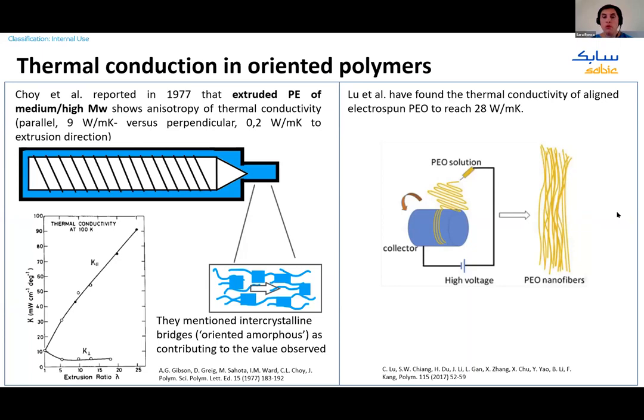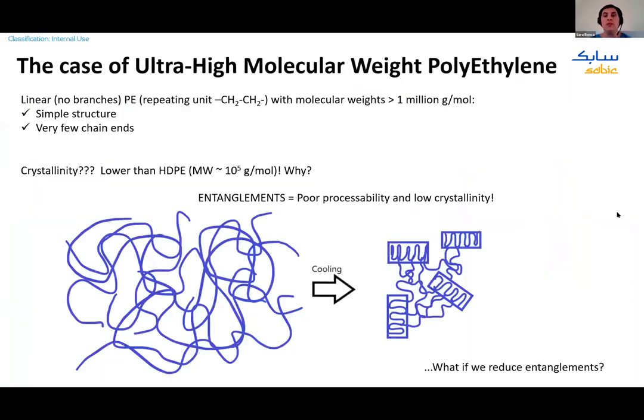But the polymer I want to focus on today is ultra-high molecular weight polyethylene. This material is basically an analog of the common high-density polyethylene. The repeating unit is the same, just CH2, CH2, and it's a linear polymer with no branches, but with molecular weights higher than 1 million grams per mole. We have the simple structure, we have very few chain ends, we should have everything. We should have a material that could crystallize very well, be processed very easily, and be oriented very nicely.